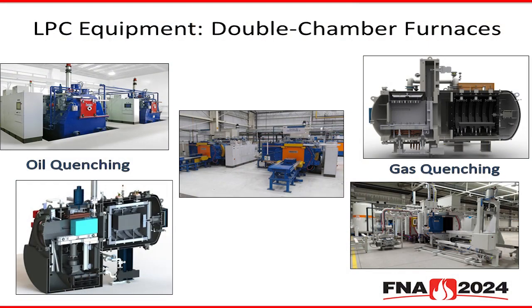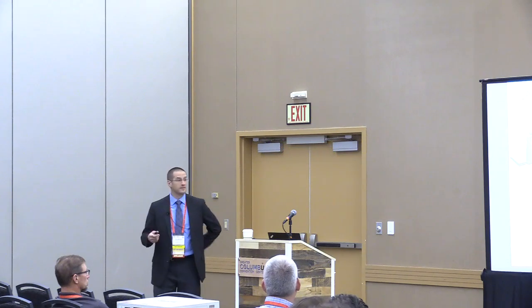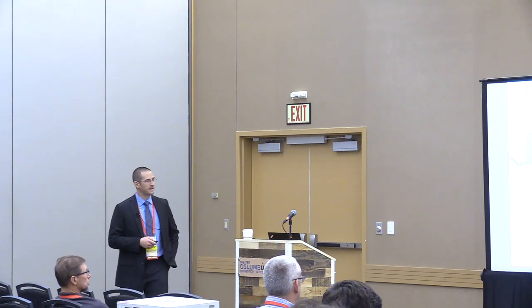And as you see, we've got a fairly wide variety of different configurations available. Now, as I mentioned about the quench rate, it may not work with gas quenching, so we have to step to a secondary configuration using a double chamber furnace to add oil to the mix, if you will, where we can handle heavier cross-section parts and more massive parts and achieve the required hardness. So here's an example of those, which we can also do in the gas quenching mode with this configuration, and again achieve a slightly higher quench rate than we would in a typical single chamber furnace.